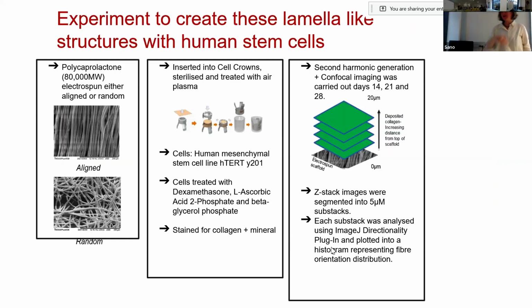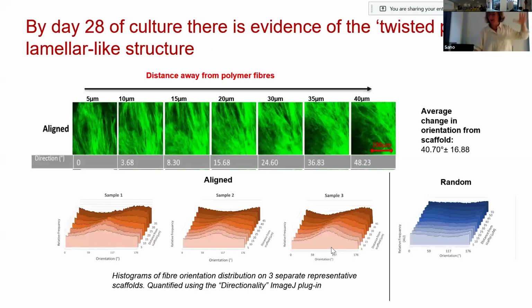So we wanted to know if a stem cell could actually make lamellae in the lab based on that system. So we used, again, polycaprolactone, aligned versus non-aligned, and grew stem cells on it, and let them build up collagen, and then imaged it using second harmonic generation imaging, which can image collagen without staining. So you can image it over time and over quite a depth, like hundreds of microns of depth.